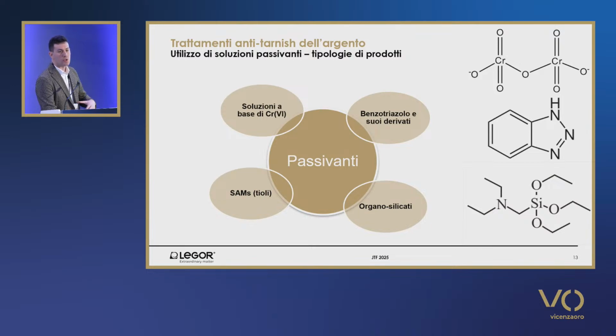Now, the most used systems are so-called passivating solutions. In the past, CR6 solutions were used with a high resistance to tarnishing, but they are based on CR6, which is highly toxic. And then other solutions have been used. Benzotriazole, for example, is more prone to copper than to silver, and so it is often used for copper alloys in the electronic sector.